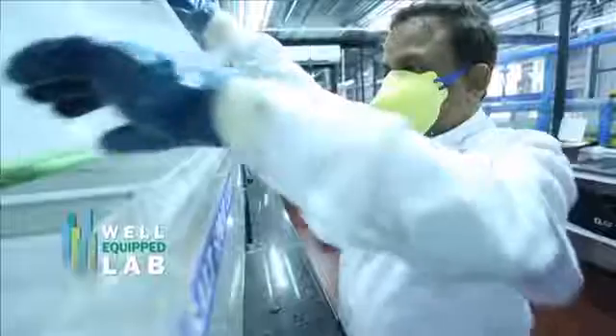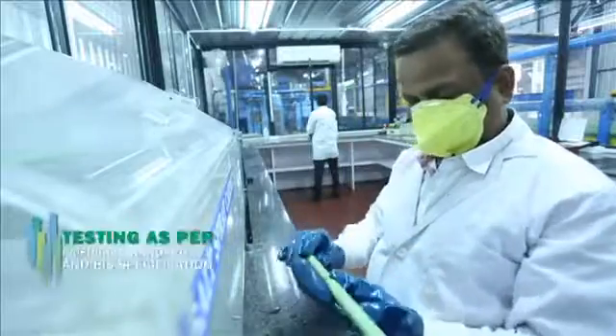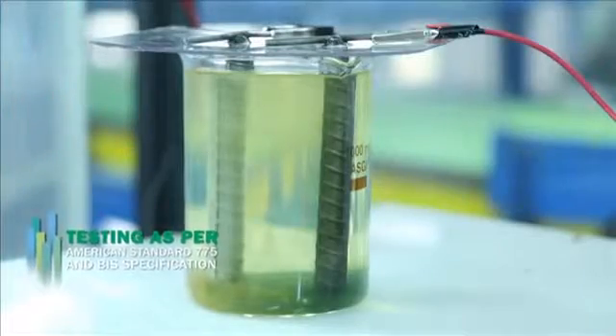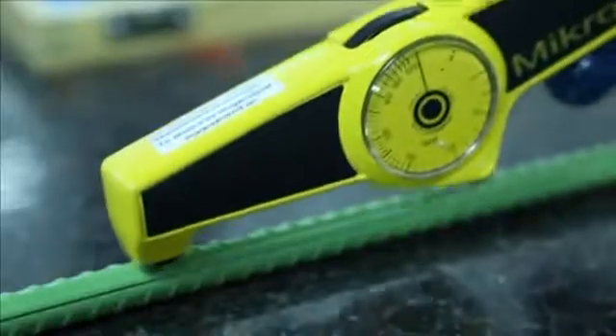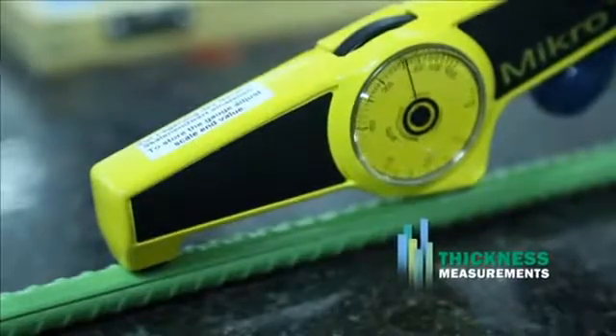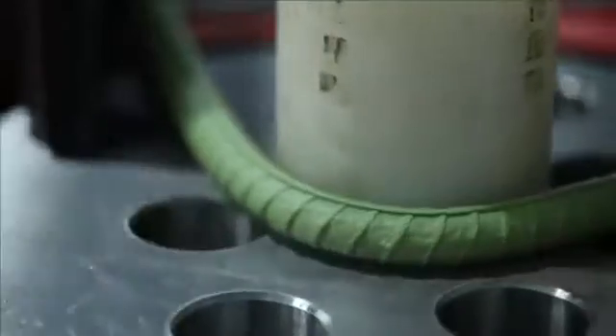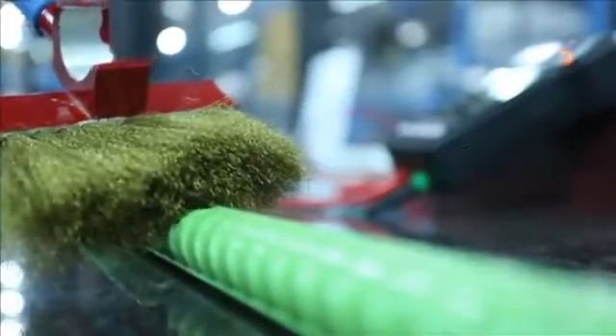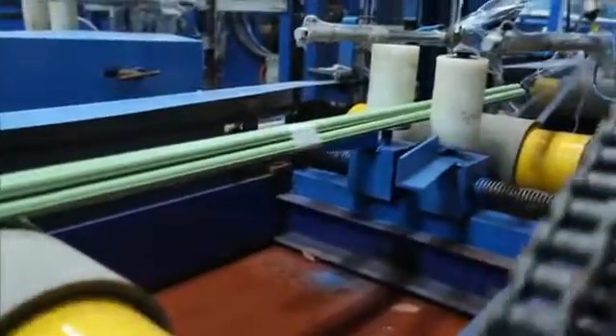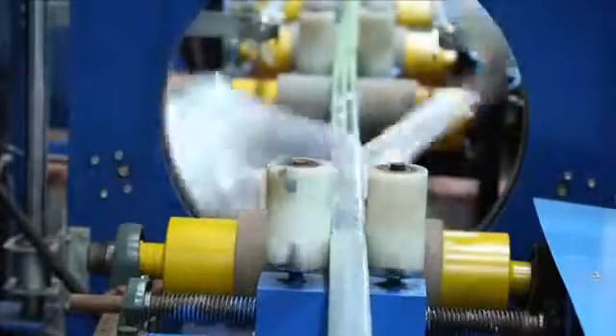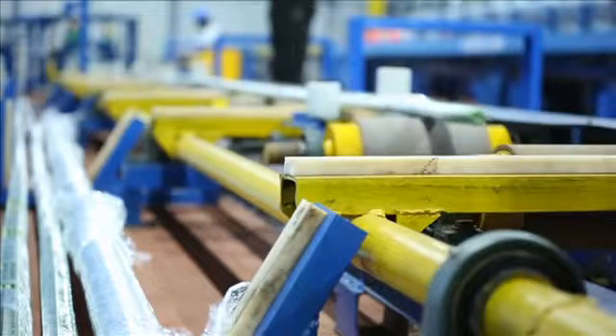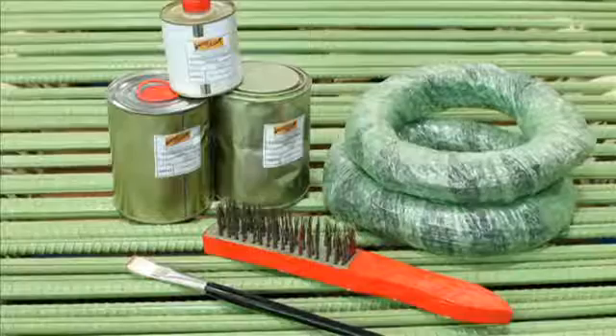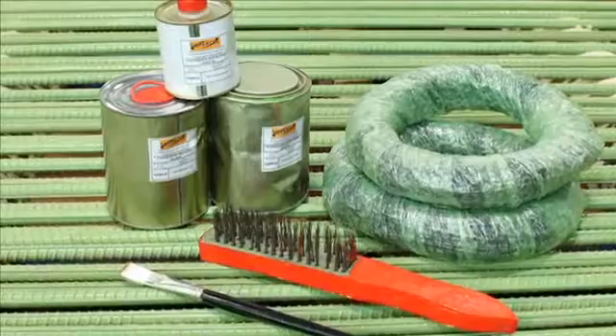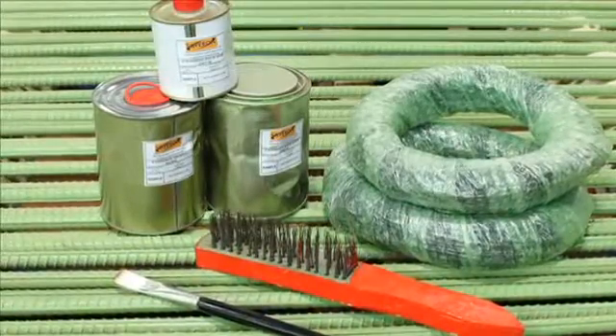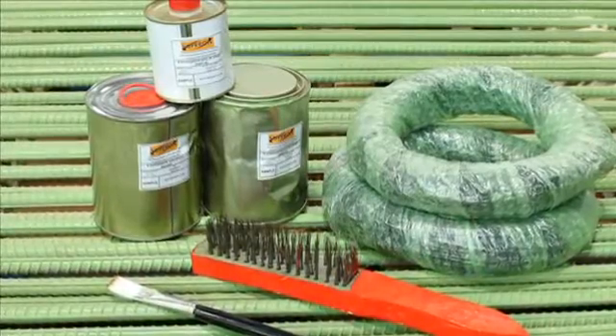In the well-equipped lab, the testing on coated bars is carried out as per American Standard 775 and BIS specification requirements. The acceptance tests usually conducted are thickness measurements, flexibility test, and holiday test. Once inspected, they are bundled straight from the epoxy coating plant. A multi-layer poly-packing wrapping is done with an automated packaging machine to prevent needless exposure of the epoxy bars to vapor, sunlight, and ultraviolet rays. Besides all these, brush and polymer-coated wires are supplied free of cost to mend any scratches caused at the construction site while cutting and welding.